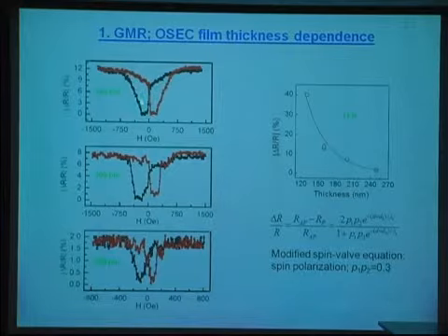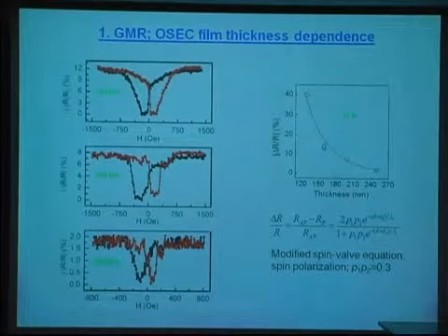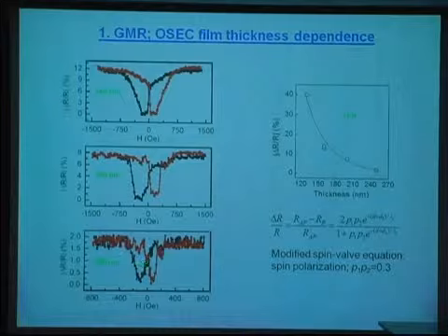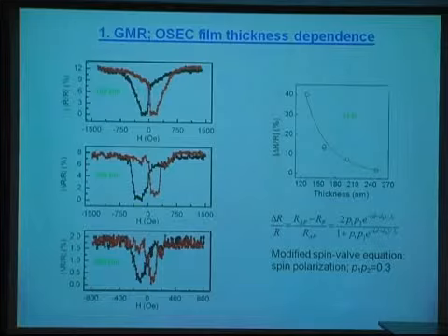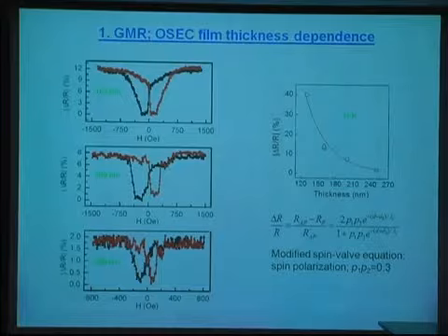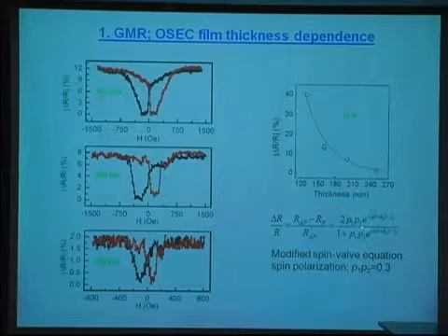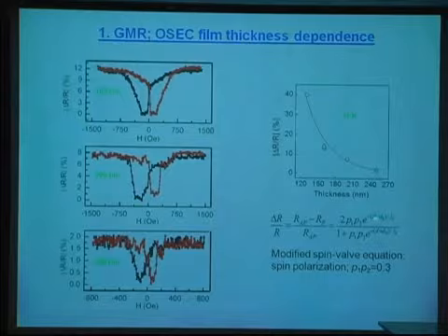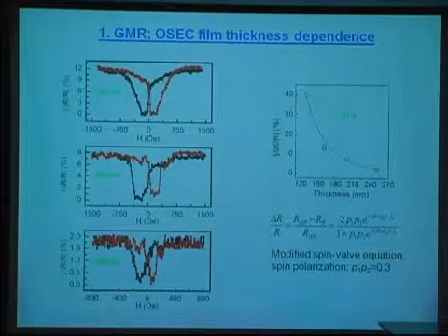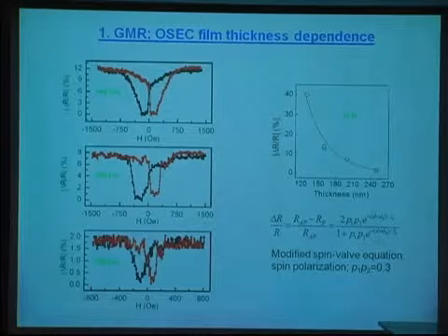They made Alq3 organic spin valve devices with different thicknesses, and you can see the thicker the device, the smaller the magnetoresistance. The magnetoresistance here is just less than 2%. They plot all of the thickness dependence of the magnetoresistance in one plot here, and fit those experimental data with the well-known modified Julliere model, in which P1, P2 are the spin polarizations of the electrodes, D is the thickness of the device, and lambda S is the spin diffusion length. And D naught is something they call the ill-defined layer.